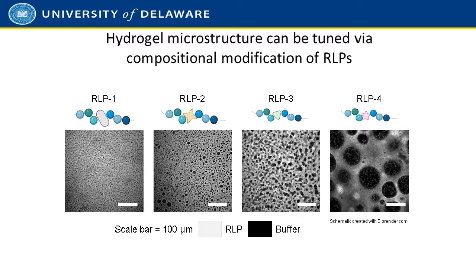What's important for us is that when we change the sequence of the RLPs then, we have a very easy way to tune the length scale of the dimensions of these RLP phases, again, shown in the light color across hydrogels with different structures. So I'm not at liberty yet to reveal what these sequences are, but suffice it to say that we're able to control not only the kinetics of the phase separation, but the cell binding properties as well.